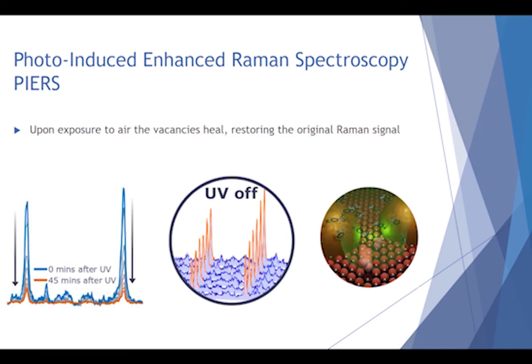However, after the UV has been switched off, and upon exposure to either air or water, the oxygen vacancies heal up, and therefore a steady decrease in the Raman signal can be seen, eventually returning back to the original Raman signal. Therefore, we can use the changes in Raman to track the formation and healing of oxygen vacancies over time.